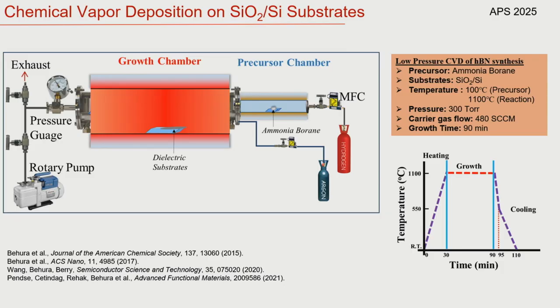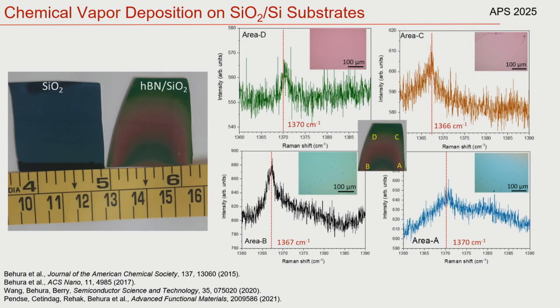It's a little bit harder. As you can see here, you use significantly higher temperatures, longer growth times, and more precursor than you would with any catalytic substrate. And it requires a lot more tuning to actually get it on there in a very even deposition. And then beyond that, you'll also notice that we have to vary pressure quite a bit, as well as the gases that we use. But luckily, we've actually been successful, even with all these changes.